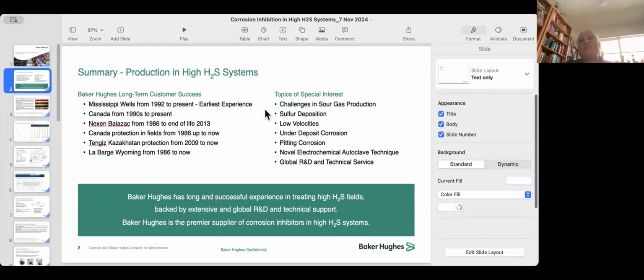Now, when you have high H2S, the phase equilibrium is interesting in the sense that you can get sulfur deposition, and sulfur deposition can cause very bad corrosion. So really, you're worried about low velocity lines, and under deposit corrosion is very bad. Generally, when you have H2S and it's flowing very, very fast, you don't really have corrosion problems. When you're going slow, you have problems. Generally, the corrosion problem with H2S is pitting corrosion.